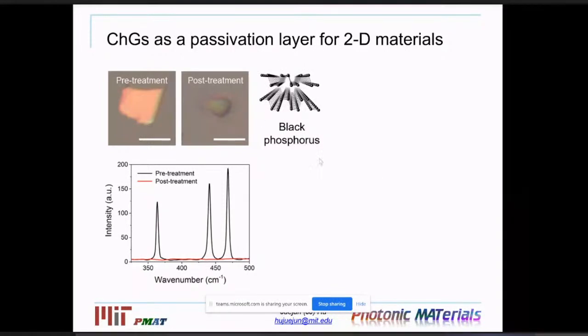Just one example here is black phosphorus. This is a narrow gap 2D crystal that's quite attractive for infrared detection. But the problem there is that it's not stable. If you leave it in an ambient environment, essentially within a few days it transforms from phosphorus to a puddle of phosphorus oxide due to the interaction with oxygen and humidity in the ambient environment. So this is what we did here. If you look at the crystal after a few days, all the crystal signature disappears in the Raman spectrum.